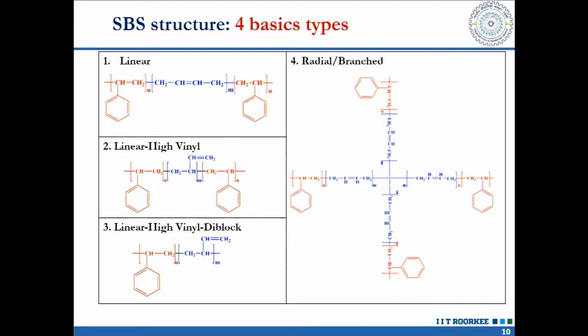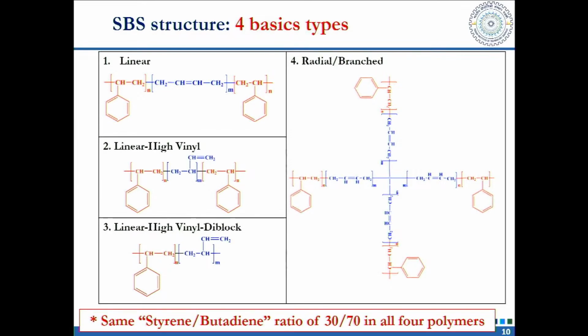So this is the chemical structure of linear, high vinyl, high di-block and the radial. The right side is the radial structure. We can see from this chemical structure that in the linear type there is a double bond in the main chain, in the middle portion of the butadiene. When the double bond shifts to a side chain, it becomes a high vinyl structure. And further, the di-block has styrene and butadiene, but again has a double bond in the side chain. When you shift the double bond to the side chain, it is very effective for the thermal stability of PMB, which we will discuss in a later slide.